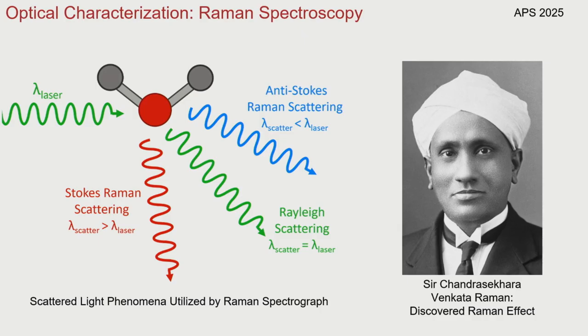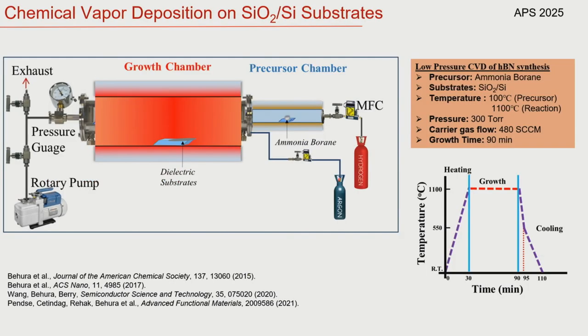visualizing the scattering of that light, you can see the vibrational modes of that actual material, and you can get a kind of molecular fingerprint of what's going on the surface. So we're specifically utilizing that to determine what we are growing. So a little bit about growing hexagonal boron nitride directly onto dielectric substrates.